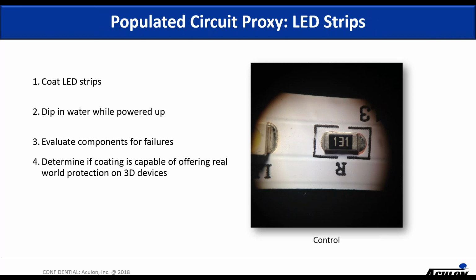So what we utilized is some very simple LED strips. They are cheap, readily available, extremely sensitive to moisture and water. They will almost immediately corrode and fail on insertion into water if they're not protected. So essentially what we do is coat these strips, dip them in water while powered up, and then evaluate them for failure afterwards. And based on this, we can determine if the coating is capable of offering any sort of real-world protection on the three-dimensional device.